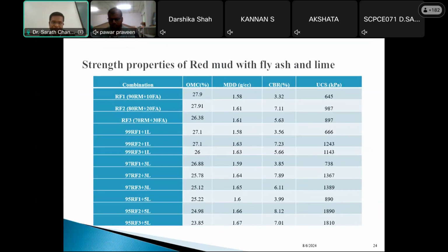And strength properties of red mud with fly ash and lime. Here, the other admixture with red mud and fly ash is lime. Here, the best combination we found is the same again. Overall, 80% red mud and 20% fly ash has given the best results, with different percentages of admixtures. Here also 5% lime has given the best value. That is 8.12% of CBR and 1,890 kPa of UCS.